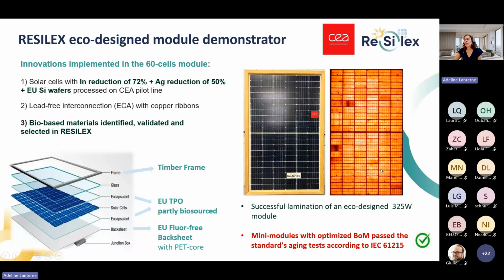With this module, the most important thing here is that all the innovation implemented have been checked, and we could pass a standard aging test. So for this optimized bill of material, we also passed a standard aging test according to the IEC standards. So that was one important result.